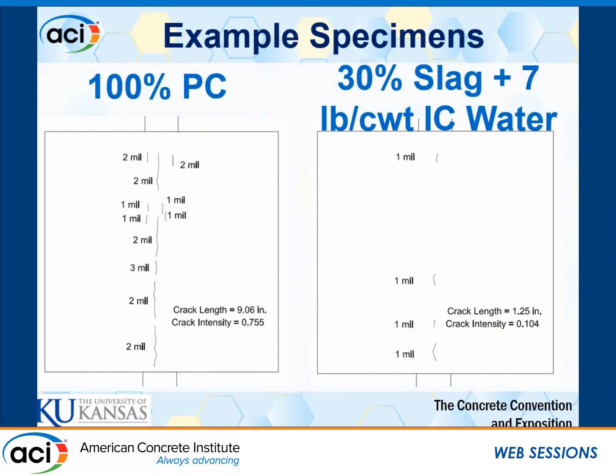So getting into some settlement cracking examples here. On the left, we have our 100% Portland cement mix. One of the more extreme cases there has over 9 inches of cracking and a resultant intensity of 0.755. And the one on the right is one of our better performing 30% slag plus internal curing mixes that had only a 1 mil wide, or maximum 1 mil wide crack and a very low crack length.